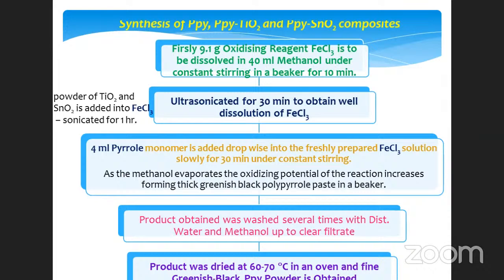All these reactions are going on in methanol, which is an organic solvent that is highly volatile in nature. As the reaction proceeds, methanol gets evaporated. Due to the evaporation of methanol, the oxidation potential of the reaction increases, and we get a good polypyrrole paste inside the beaker. A greenish black precipitate is obtained. Then this precipitate is filtered, washed properly, dried at 60 to 70 degrees Celsius in an oven, and finally a black greenish powder of the composites is formed. Next, please.